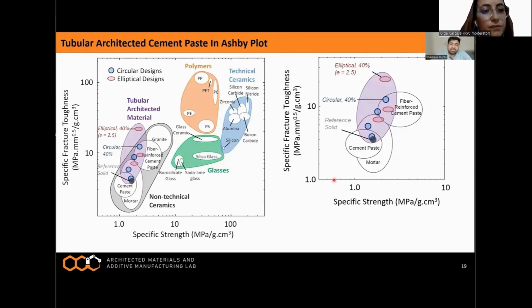Zooming into the plot, we can see that circular 40% shows specific fracture toughness close to the upper boundary of the fiber reinforced cement base, whereas elliptical 40% with the aspect ratio of 2.5 showed the highest specific fracture toughness among the tubular architected material, and it is even higher than the fiber reinforced cement.